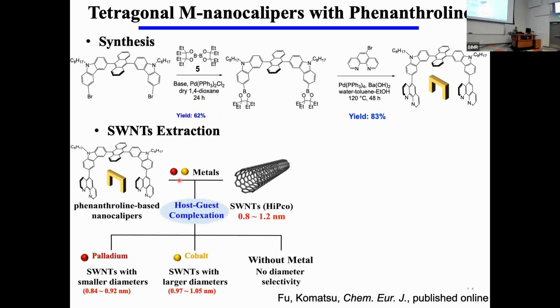When we apply this palladium to this carbon nanotube extraction, the smaller diameter range from 0.84 to 0.92 nanometer is extracted. And when we apply the cobalt instead of the palladium, we successfully separate the larger diameter carbon nanotube from 0.97 to 1.05. Anyway, we simply change the kind of metals, but we can selectively extract the different size of the carbon nanotube.